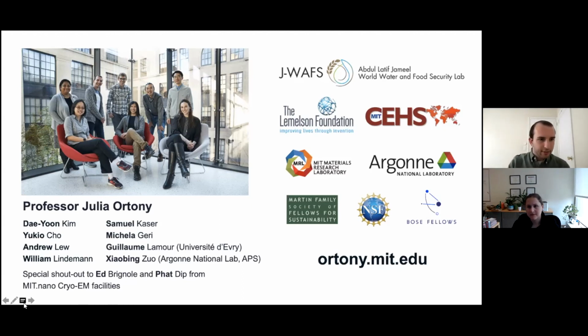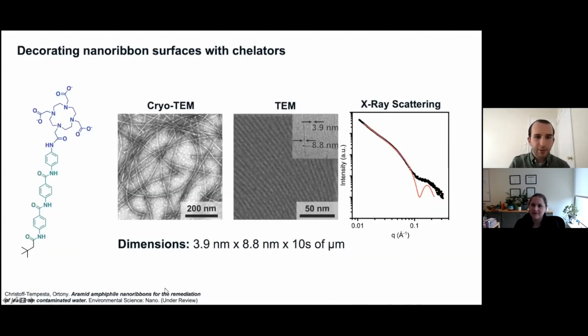Yeah, that's a great question. I unfortunately don't have a specific slide for that, but if I can go back to the molecular structure, maybe I'll even put some annotation here. The lead ion will go into this spot where the star just showed up in the center of these molecules. Each of those 4 nitrogens and the 3 carboxylic acids wrap themselves around the lead ion. So it's not any sort of covalent interaction, but it is multiple very strong ionic interactions that result in the lead ion being bound effectively to that spot. And that's what makes it difficult to remove afterwards.